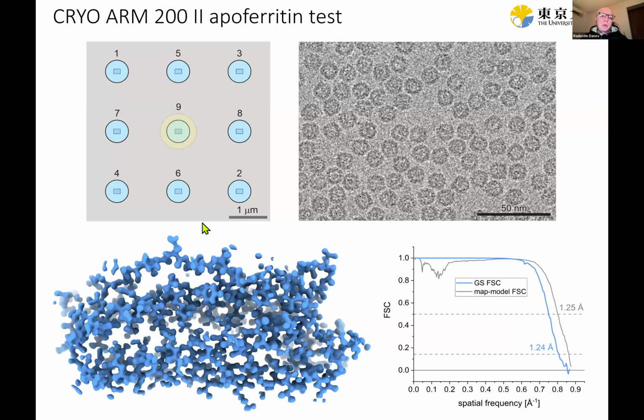Then to further test the machine, we collected apoferritin data sets, and here is the one that we recently submitted as a preprint last week, which reached atomic resolution. The configuration for this sample was using a 0.6 micron HoleyUltrAuFoil grid. This improved the stability of the sample. We are also collecting a single image in the center of each hole and having the beam uniformly illuminating the hole all around. This was to minimize beam-induced specimen motion. Here you see an example image from the data set. Of course, the apoferritin is nicely visible as spherical molecules.